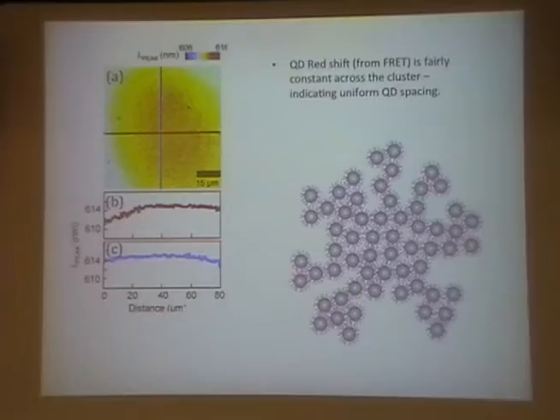We also saw from our PL imaging something that correlates with this model. So if we take a look at one big cluster here, a severely big one, this is also a wavelength image. You can see the redshift is approximately the same all throughout the core. It's not getting denser and denser into the middle. So it looks like we have the particles randomly but close packed within the center of the cluster, and then on the outside they start to get a little further apart and a bit more random.